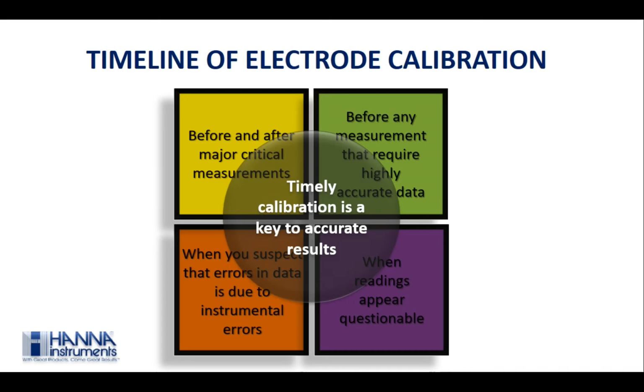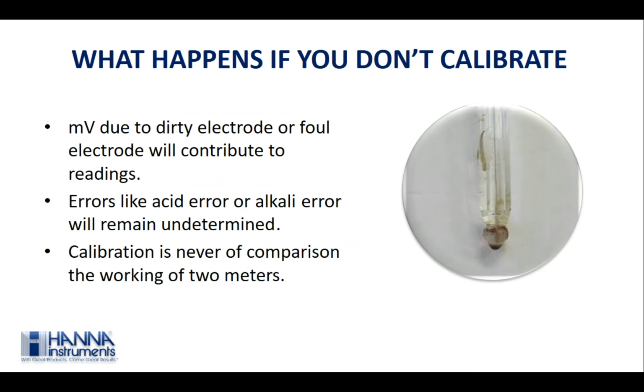But what if you don't calibrate your electrode? The errors due to many factors will contribute to your reading. It might be due to deposition or a dried pH electrode. The millivolt generation by the deposition on the electrode will add on to the millivolts of the buffers or samples, thus leading to a higher reading. Other than this, errors like acid error or alkali error will remain completely unidentified.